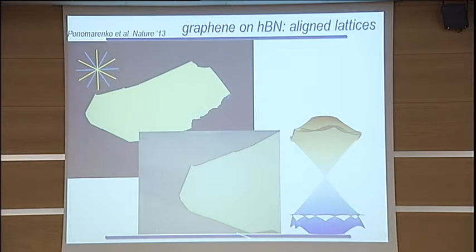actually. So this white bit is exactly this one, and then on top of that, that's graphene, that's bilayer graphene, and what we did here is we aligned the facets of boron nitride with the facets of graphene, and then of course we don't know which one is zigzag and which one is armchair, but at least you have a 50-50 chance now to align the two crystals perfectly.